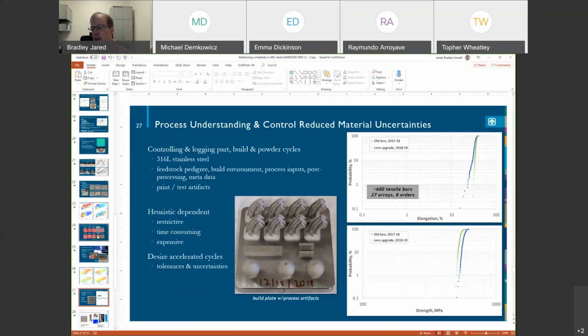That's one thing. The other thing is we did do the work to characterize our machine, and we eliminated a lot of the variability and the challenges. After the fact, we learned on the 17-4 material that, for example, the material was printed on multiple machines, potentially with multiple different settings. And so there was all kinds of variation that was occurring there, right? And so, again, the piece here is to understand your machine and to know where your settings are.